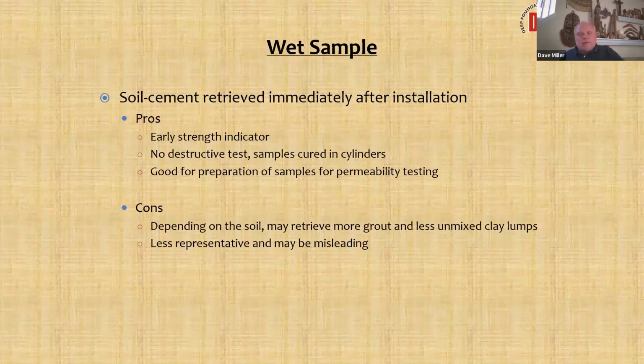So wet sampling is one way to achieve samples without the coring. It's quick and dirty. You take the sample right after you've completed the wall while the material is still fluid, and you can mold it into cylinders, typically 3x6, and you can mold several cylinders, cure them under certain conditions, and then test them at various ages, like 3, 14, 28, and you can even hold some samples for longer strength. The benefit of the wet sample is that it's an early strength indicator.